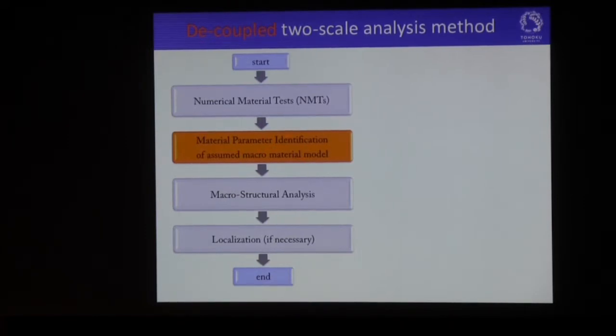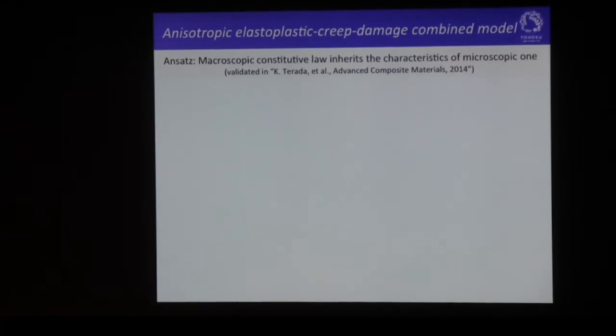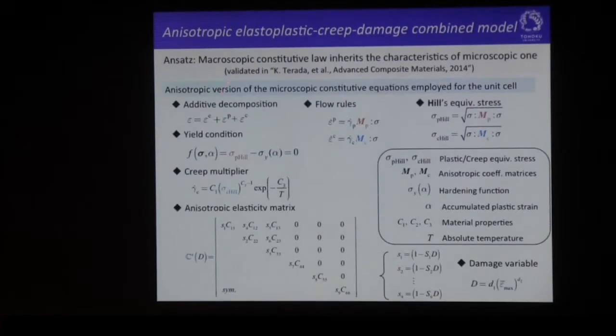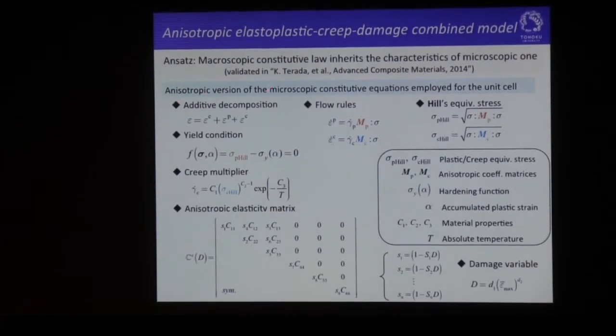And we have to assume the macroscopic constitutive equation to represent such kind of macroscopic response. For that purpose, here I put the ansatz that the macroscopic constitutive law inherits the characteristics of the microscopic one. That is validated in this article. Then I employ the anisotropic version of the microscopic constitutive equations employed for the unit cell. That is the anisotropic elastoplastic creep damage model.